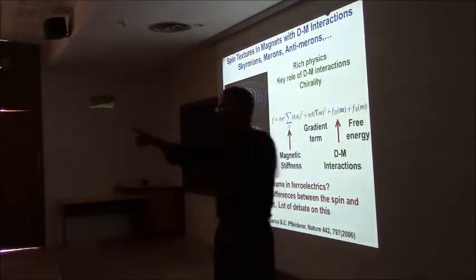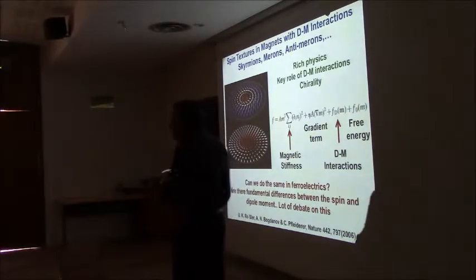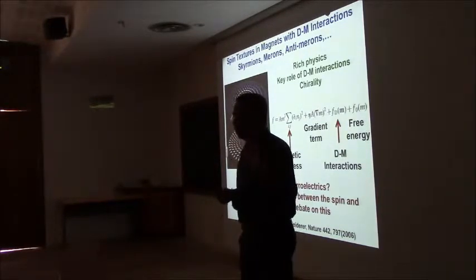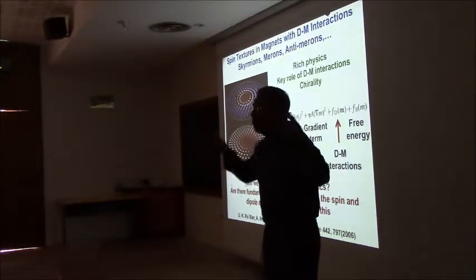And the other question has always been, if you look at the ferroelectrics community versus the magnetism community, there are two extreme cases. In the case of magnetism, typically, unless you go to very hard ferromagnets like neodymium-iron-boron or samarium cobalt ferromagnets, typically ferromagnets are dominated by exchange interaction. You take a piece of iron, the exchange interaction is very strong. The anisotropy terms in ferromagnets typically is lower. And therefore, all the behavior, the switching behavior, the nature of the domain walls are all governed by exchange interaction.